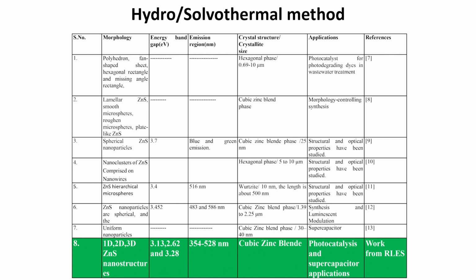The nanoclusters of ZnS comprised on nanowires have been grown with the hexagonal phase crystal structure, and the crystallite size is of the order of 5 to 10 micrometer. And here also the structural and optical properties have been studied. The ZnS hierarchical microsphere has an energy band gap of the order of 3.4 electron volt.